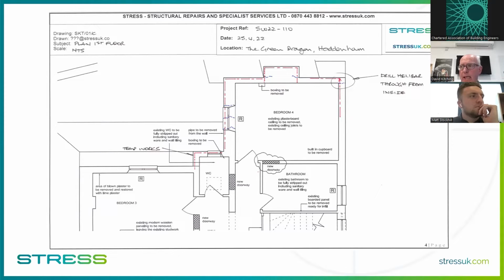Now, little tip here, if you are rejoining two walls, maybe it's a rear wall and spine wall, what we often see is people running heavy bar around the inside of the wall, which is not quite right, because if you can imagine, if that gable wall now wanted to move out, if you were putting the bar around the inside of the corner, all it would need to do is just pull the bar horizontally out of the bed joint. And that's not where its strength is. So you want to actually drill right through to the outside, return the bar on the outside. So when that wall wants to try and move out, it will put the bar in the flank wall under tension rather than under sideways pressure. And you use the tensile capacity of the rebar.